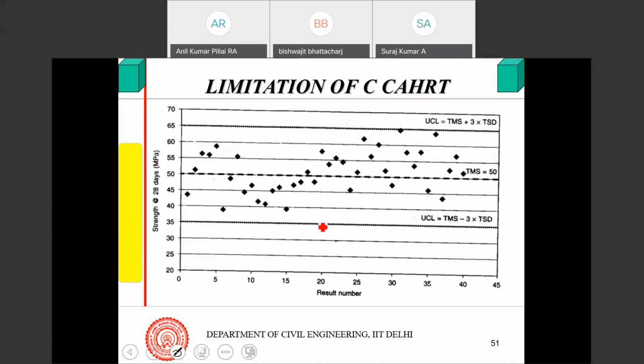But the charts have some limitations. The 28 days strength could be predicted strength, as I said, through an accelerated test, so that I can take action and verify this later on. The limitations are that it does not give me any other information than whether I am within the range or not. If it goes beyond for some days, I can't tell since when it is a trend or a random variation.